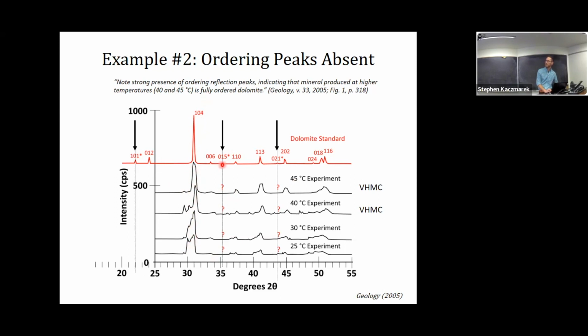But when we look for these ordering peaks, like the 101, the data were not collected down that far, so we can't evaluate that one. The main ordering peak, the 015 here, is clearly missing in their higher temperature experiments, and really in all their experiments. The 021 peak is also missing. So what we think here is that they've got the same kind of phase that Goldsmith and Graf had, which was proto-dolomite, a calcium magnesium carbonate, but it lacks cation ordering.